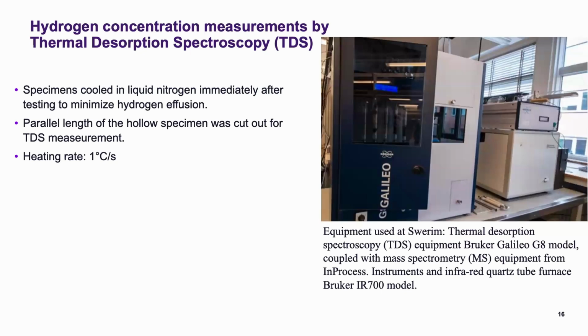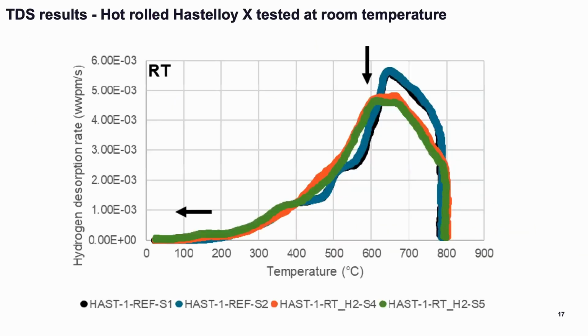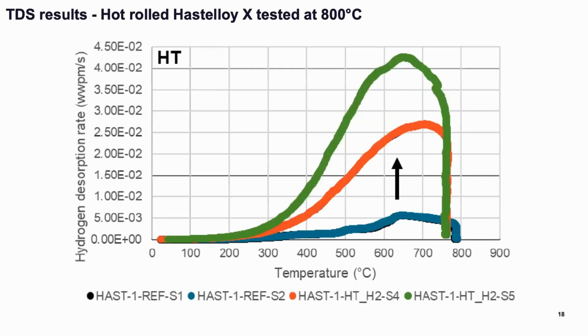I can quickly mention the TDS measurements. For the hot rolled Hastelloy X at room temperature, we have more or less no hydrogen uptake measured. We measure a bulk measurement of the whole parallel length, so it's not surprising. But maybe we see some shift to weaker trapping sites. When we test the hot rolled Hastelloy X at 800 degrees, we have a clear hydrogen uptake. This difference between the two tests, I think, is related to what I mentioned previously, that we can get effusion of hydrogen after the leakage, but before we manage to cool down the specimen.